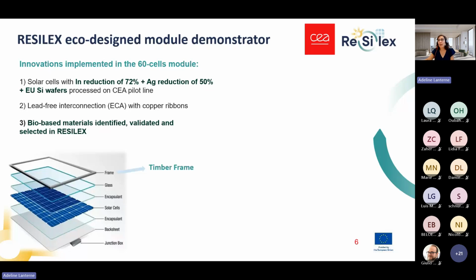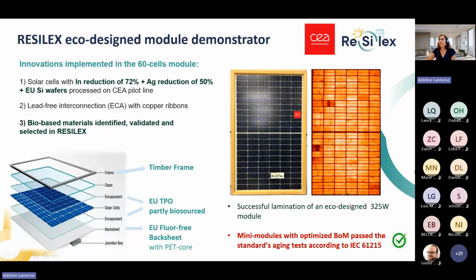For instance, we used a timber frame instead of an aluminum frame. We replaced the standard POE encapsulant by TPO, which is a thermoplastic olefin film, which was partly biosourced, and we also use a European fluor-free backsheet. With all this, here are the results of the demonstrator: we had a successful lamination of all the materials, and we end up with an EcoDesign 325 watts module.